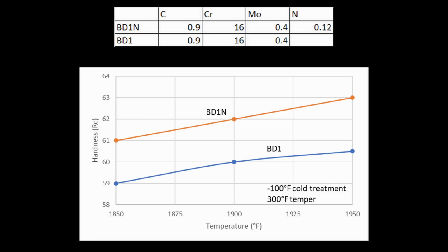A 300-degree temper is about as low as I ever recommend for most steels, because that gives you a little more toughness and ductility versus as quenched or no tempering, but usually with similar hardness to as quenched, sometimes even a little bit higher. But the bottom line here is just with the nitrogen addition, you get a couple points more hardness for a given austenitizing temperature. That's the temperature you heat it up to before quenching. Normally when you austenitize higher, you put more carbon, or in this case, carbon and nitrogen in solution, so that when you quench, those little interstitial elements are there to increase your strength. Adding a little bit more nitrogen to the BD1 means that you get higher hardness after quenching. So it's all good news.